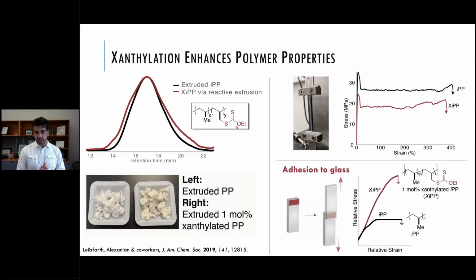So to test that, we did this adhesion experiment where we essentially just glued 2 glass slides together with our new material and pulled on that until it broke. And we found the addition of this chemical functionality improved the adhesion strength of our material 2.5 times compared to polypropylene. So we've created a material in an extruder just by kind of sprinkling in a little bit of our reagent that has similar properties to polypropylene, but now adheres to materials 2.5 times better. So that was really exciting.